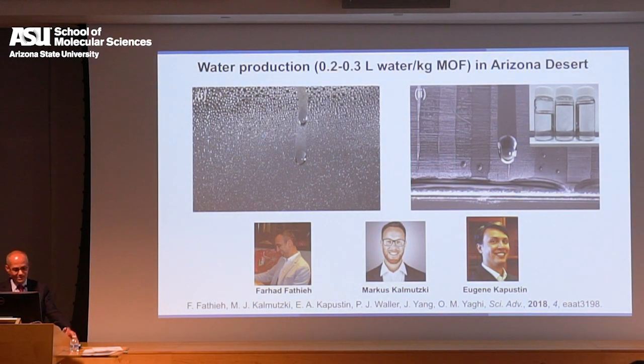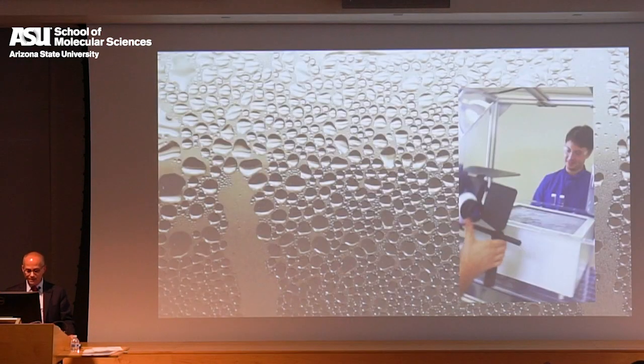So these are the 3 students who were doing this experiment in Betty's backyard. You can see here the production is 200 milliliters to 300 milliliters. That's a cup of water. This is 236 milliliters. So it's a drink of water from a kilogram. Completely unoptimized, and then we discovered that not all the MOF is being used because air has to diffuse further down into the cake of MOF. But now we've gotten a lot better, as you will see, in exposing the MOF to air.